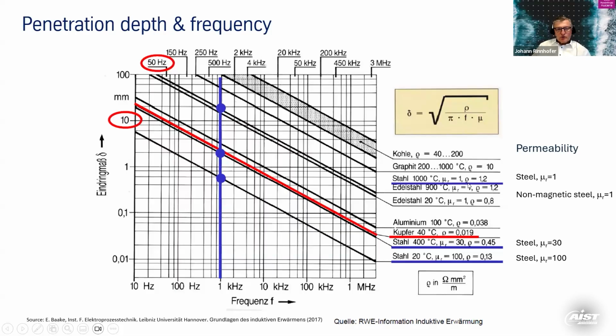It's also very significant to note that steel, as long as it is magnetic, is somewhere in this area. So steel at 20 degrees with a permeability of 100 reacts completely differently in comparison to a non-magnetic steel, or a steel above the Curie temperature, which is more than 770 degrees. Then it turns into 1, from 100 to 1. So the heating is completely different in the high temperature range.